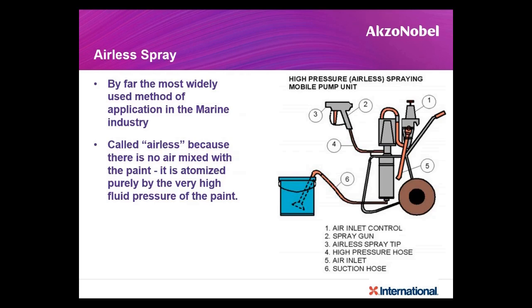Airless spray equipment are very high pressure equipment. They are pressure multipliers. The initial pressure at the pump suction to the final pressure at the gun tip could be multiplied by 30 times and 40 times and 60 times. Now 73 times also. Depends on that. Advantage of airless spray is it can take very thick paint and deliver very high thicknesses. Productivity will be very high. For example, you can develop thicknesses up to 2 mm and 3 mm using a single spray. But they are very high pressure equipment. It's also got its own safety challenges. Specialized applicators do this job.